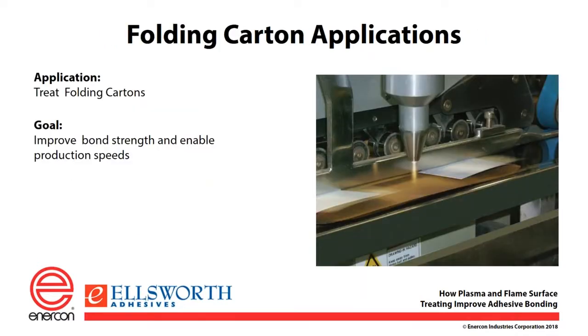Folding cartons is another application. You're treating the bond line, the glue lines of the carton. Depending on the material that they're using, they'll use different adhesives on these cartons, and occasionally there'll be a little bit of an issue with the material and the printing on the material, so it helps the bond if you use a plasma to treat the bond lines.